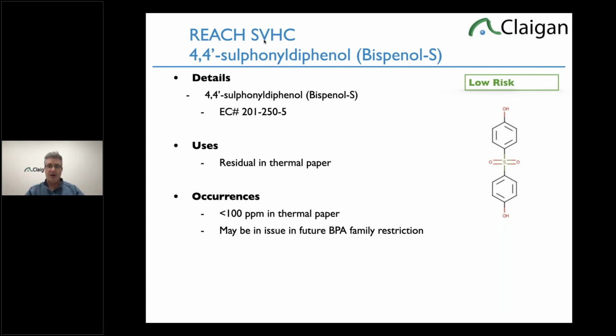It usually has sub 100 ppm, usually in the 30 ppm range of bisphenol S. So if you have thermal paper printouts, they're almost always going to have bisphenol S on them. We test multiple manufacturers, because we have a lot of alternative suppliers for our internal labels. They all have it, in differing amounts, but well below 1,000 ppm. Someday, if they ban this under the BPA family restriction, there might be some problems depending on what concentration they go with, but it's low concentration in thermal paper, well below the 1,000 ppm declarable limit. So those are the 5 low risk ones.